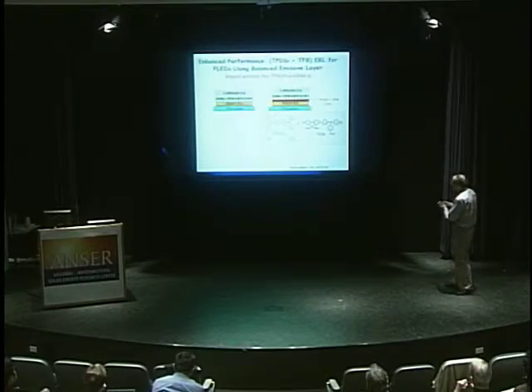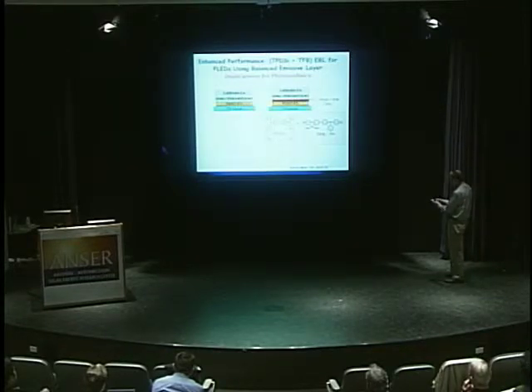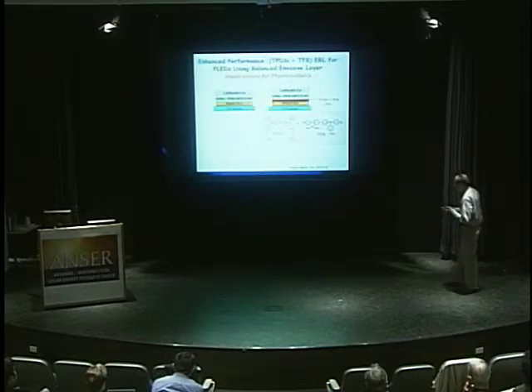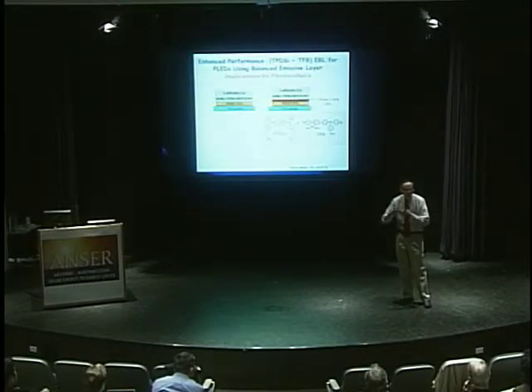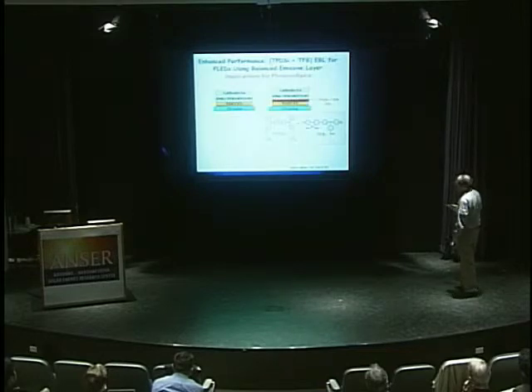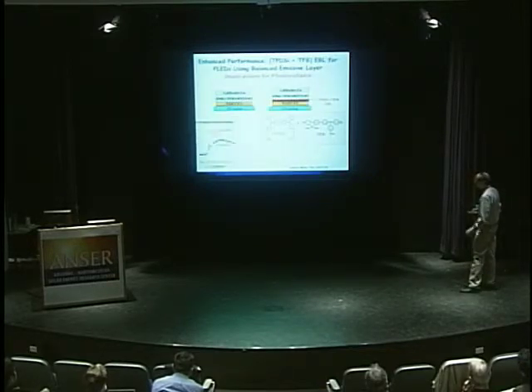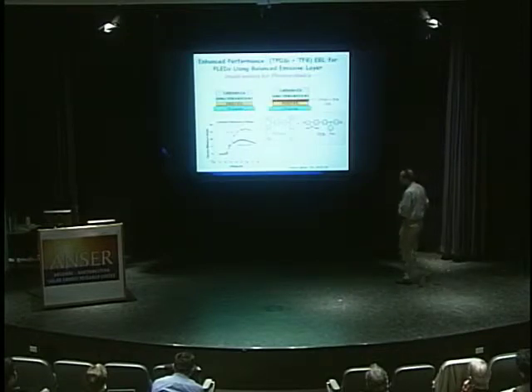So Henry reasoned, if this is true, let's take it one step further. And this is a device that now has a really optimized emissive layer. And what we concocted, or what he developed, was a blend where we take the TPD-Si2, remember this was our injection layer with chlorosilane groups, and we mix it with a good hole conducting polymer, and in air, on spin coating, the chlorosilane groups cross-link, and so we make a very dense polymer. It's covalently bound to the ITO. It has a hole mobility of about 10 to the minus 3. It's optically transparent and very robust, and it makes very nice polymer light-emitting diodes. So without triplet sensitizers, we had 17, 18 candelas per amp. So you can make a very good polymer light-emitting diode with just a few nanometers of this.